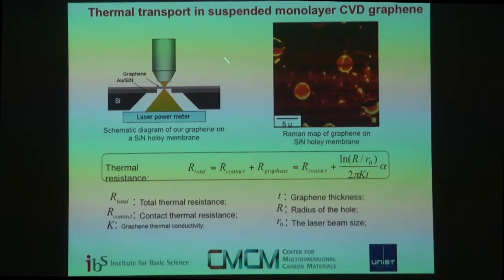So Alex Balandin's group had shown that Raman, a non-contact measurement of thermal conductivity, could be done. They had used the Scotch tape exfoliated materials, so rather than an analytic solution as a consequence of a circular geometry, they solved by using finite element methods because they had a kind of irregularly shaped flake that was spanning a trench that they configured their Raman experiment on. So their very important work set us up to do these experiments with CVD graphene where we could have a simpler geometry, the so-called Corbino or circular geometry.